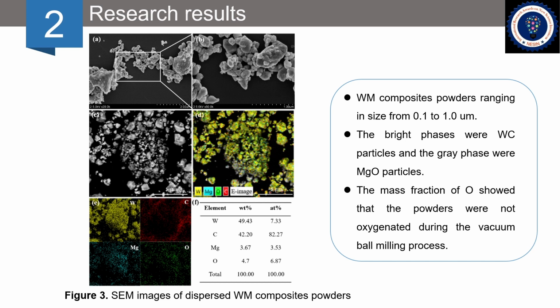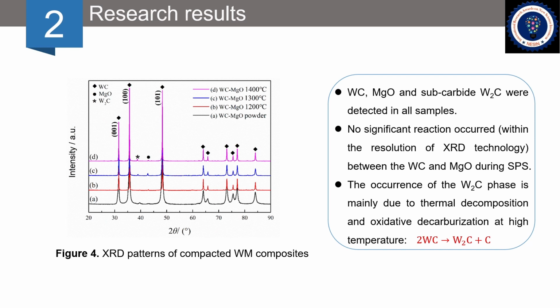Figure 3F showed the mass fraction and atomic percentage of 4 elements. It can be seen that magnesium and oxygen content were consistent with the experimental values. In addition, the mass fraction of oxygen showed that the powders were not oxidized during the vacuum ball milling process. Figure 4 showed the X-ray diffraction patterns of A to D sintered WM composites with different sintering temperatures. According to Figure 4, tungsten carbide, magnesium oxide, and subcarbide tungsten carbide were detected in all samples.